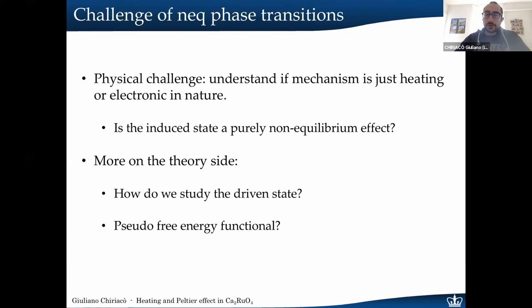Now, understanding how these non-equilibrium phase transitions work is also a challenge, not only from the experimental point of view, so not only from the point of view of modeling what's exactly happening in the material, but also from a more theoretical standpoint. So the first issue, of course, is to understand whether the mechanism that is driving the transition when you apply the electric field to your material is just electronic in nature, so you are messing around with the structure of the electronic model, or you're just heating up the system. So it's sort of a pseudo-equilibrium transition in which you just raise the temperature of the system.